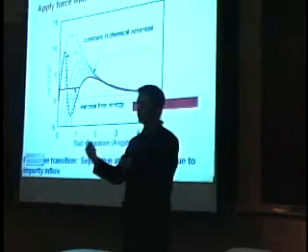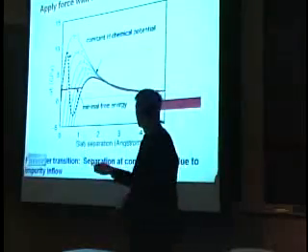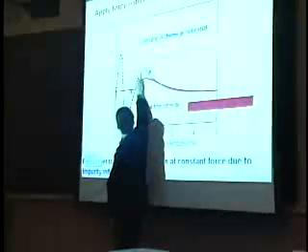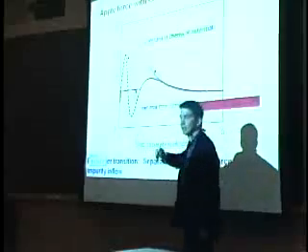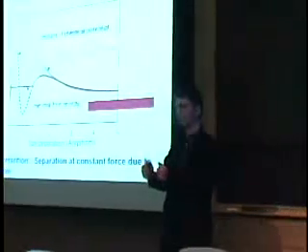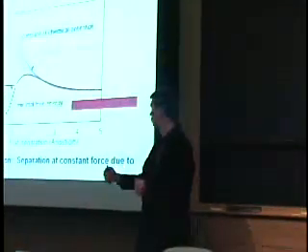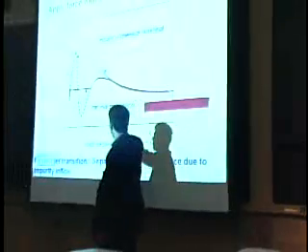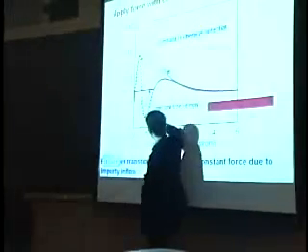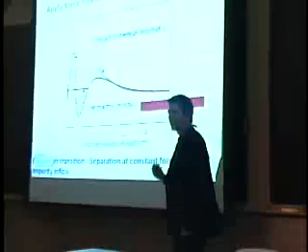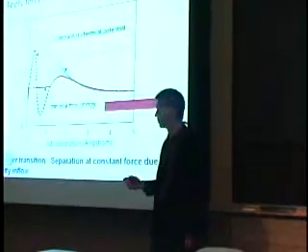It sort of makes sense, as you pull, the force goes up, no surprise, and then you reach a critical point of maximum force. At that point, you're unstable because essentially the force as you pull further goes down. So on the downslope, you're essentially unstable. But look at the red line. This is a chemically equilibrated system, and it behaves very differently.